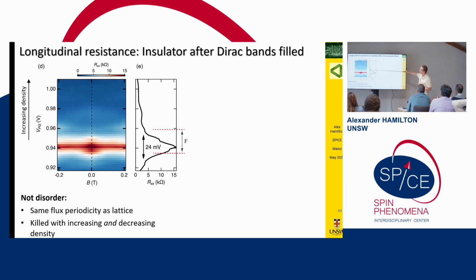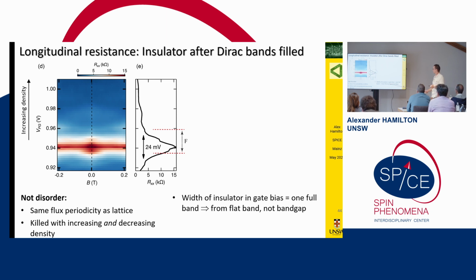If we take the width of that resistance peak, it's about 24 millivolts in gate voltage, which from our previous calibrations we know corresponds to exactly one band of electrons. It's not consistent with a single particle band gap, which would take about 1 millivolt in electrons. It's 20 times too big. So that strongly suggests that whatever this insulator is, it's coming from the flat band. So we're very interested to continue understanding that. And from the theory, we know that for the potentials that match our data, U on site divided by T is about 50. So we're very much in the strong correlation regime.